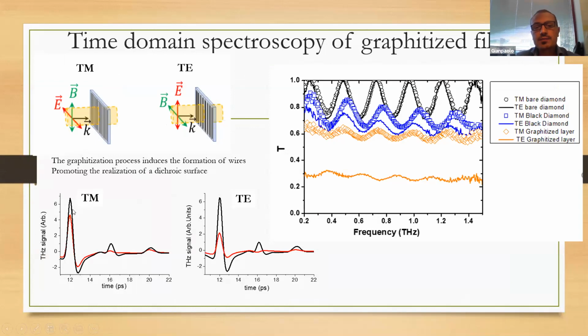The black curve is the curve obtained just passing through the diamond, not processed. Indeed, we can see the Fabry-Perot etalon effect. The red curve is the electric field, the terahertz signal passing through the sample, the graphitized one. This is for the graphitized layer. What is interesting here is that the first reflection in TM, so look at the red curve, is following the same phase of the impinging signal. Instead, in TE there is a pi shift.